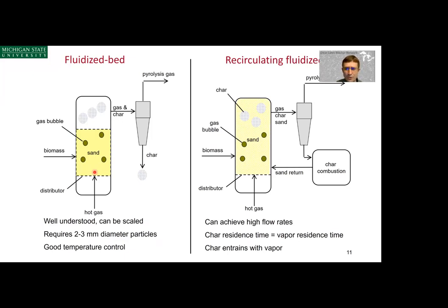You typically don't get the same yields of biochar with fast pyrolysis as with slow pyrolysis, on the order of 15 to 20 weight percent for fast pyrolysis, whereas you can get 35 to 40 weight percent biochar yields with slow pyrolysis. Nevertheless, if liquid fuels are needed, and if liquid fuel economics from fast pyrolysis systems can be supported, biochars could be produced in relative abundance because of the magnitude of the demand for liquid fuels.